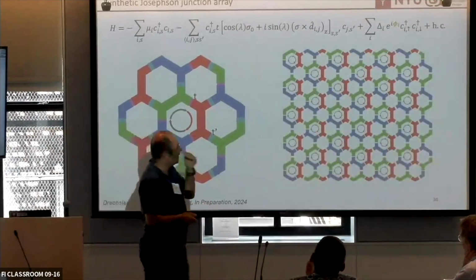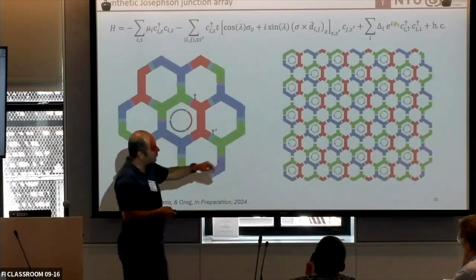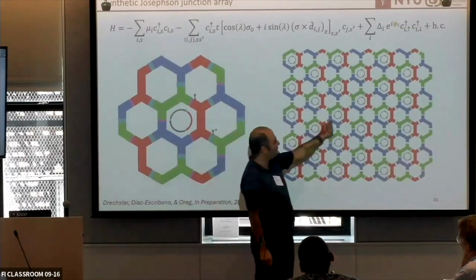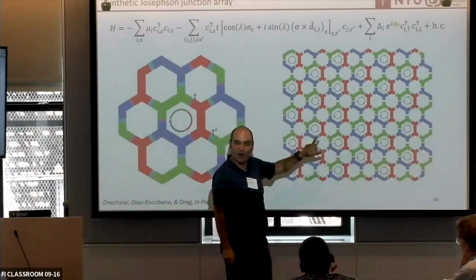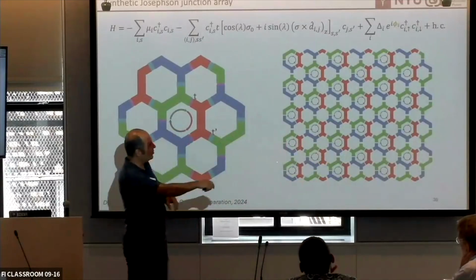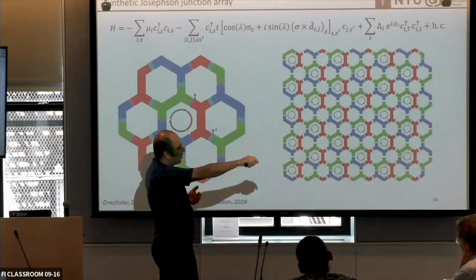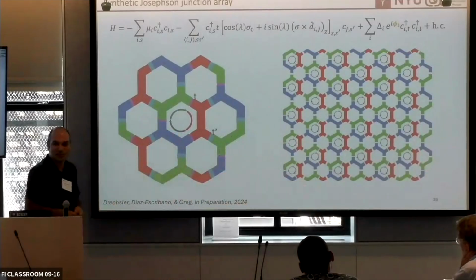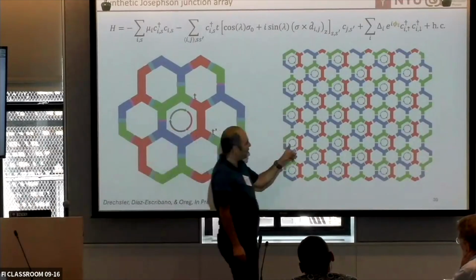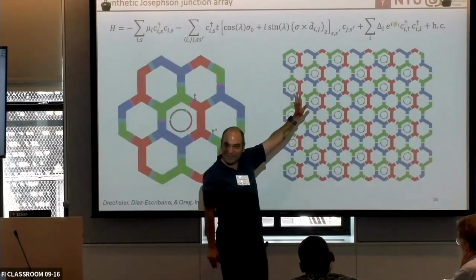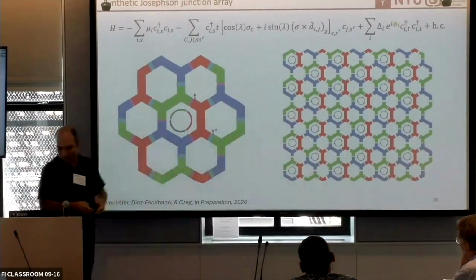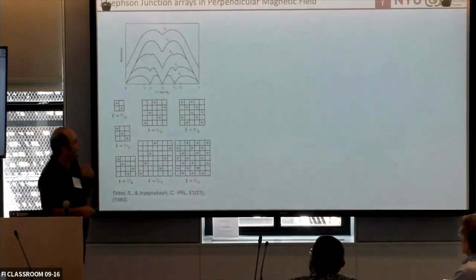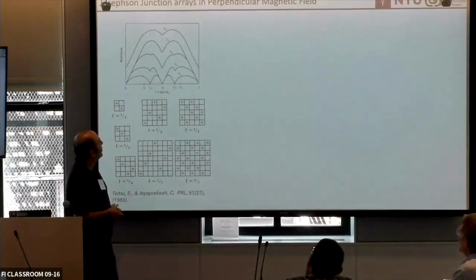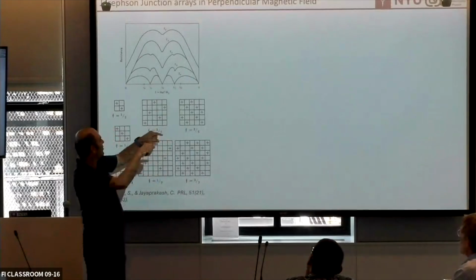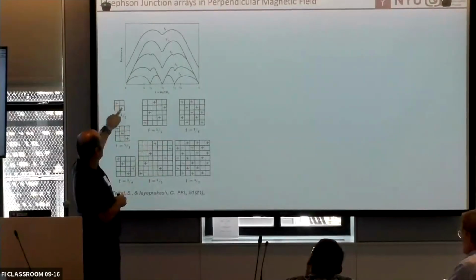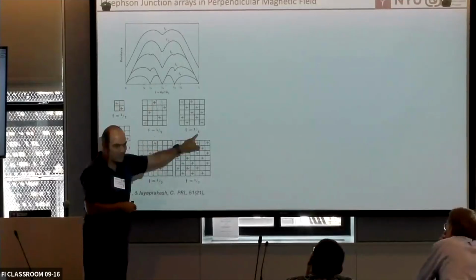So for this particular case, at least theory argues that if we put the right number of these fluxes inside and they phase wind the way we want it, then you can actually get a Majorana that is chiral and goes around and basically in its phase transition, right? So I'm going to call the number of these fluxes per the whole unit cell F, the filling factor. And we're going to try to tune some of these. Some of these trivial experiments have been done way back in the 90s. And basically, you just make this, crosses. And by putting a flux out of plane, you see a filling factor of 1/2, 1/5, 2/5.